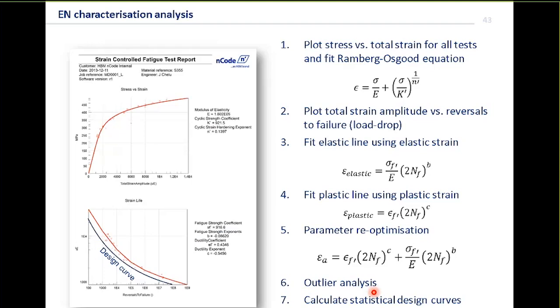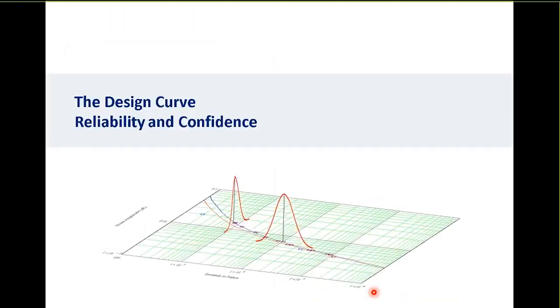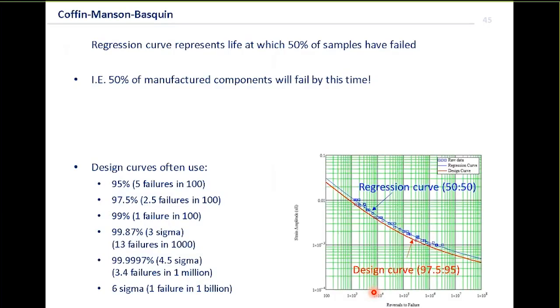Okay, so what is the design curve? Well, that regression curve is the best fit curve through the data. We call that the 50-50 or the B50 curve. And what that's telling us is that half of your samples have failed at that point. So we don't necessarily want to use that for designing things. So instead, we create a design curve. This is using so many standard deviations from that regression curve in order to look at it.